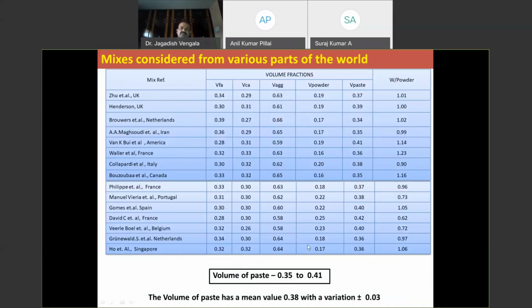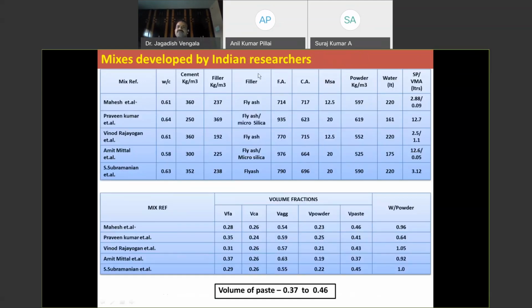So when you look into these mixes from various parts of the world, you can see the volume of paste varies between 0.35 to 0.41. In normal concrete, you might have seen the volume of paste comes around 0.21, around 21% to 23%. But here, in self-compacting concrete mixes, the volume of paste varies between 0.35 to 0.41. So the mean is 0.38. And those are from other parts of the world. But when you take the mixes from the Indian scenario, the volume of paste varies between 0.37 to 0.46. Why?